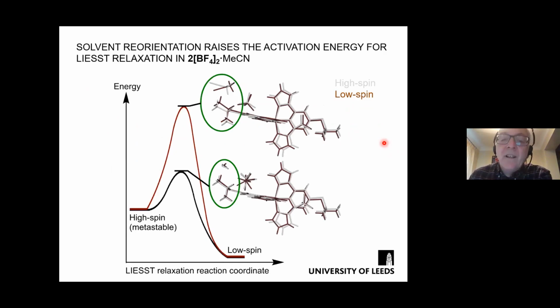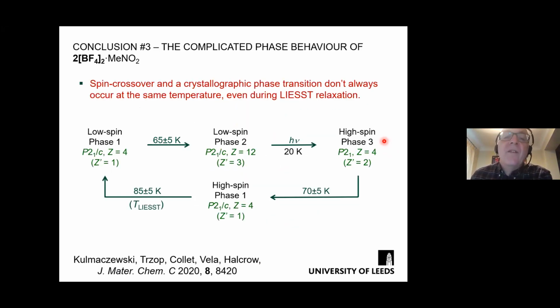The second conclusion is that the phase changes we see for this material have no relationship on the LIESST relaxation. And so as a crystallographer, you have to be a little bit careful. You might see a phase change and a spin crossover, but this does not mean that they occur at the same time. It may be that the phase change and the spin state change occur at different temperatures. So as a crystallographer, you have to look carefully to understand exactly what is happening.